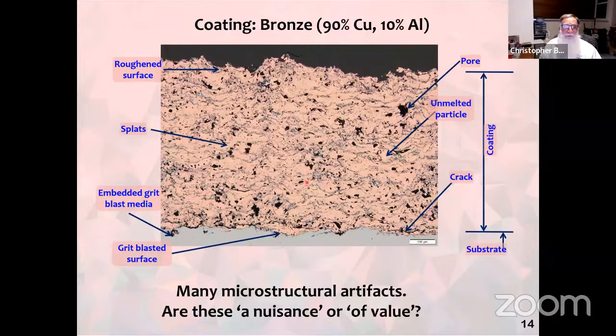So here is an example of the architecture of a very simple bronze coating, copper aluminium, on a grit blasted substrate. And we have all of these artifacts. We have splats, embedded grit, we've got cracks, we've got unmelted particles, we've got pores. So the question is, are these microstructural artifacts a nuisance?